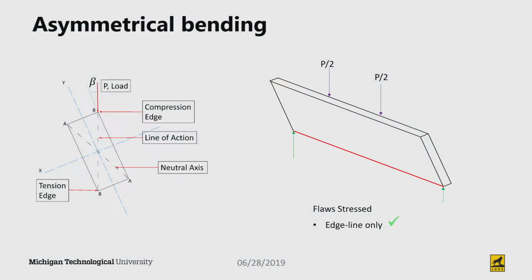And we can come up with an angle based on our sample size to where we put one edge in complete tension, which is what we're interested in, whereas the accompanying edge of that same edge face is along the neutral axis, which means there should be very minimal stress on that other edge. So we've basically isolated one edge.